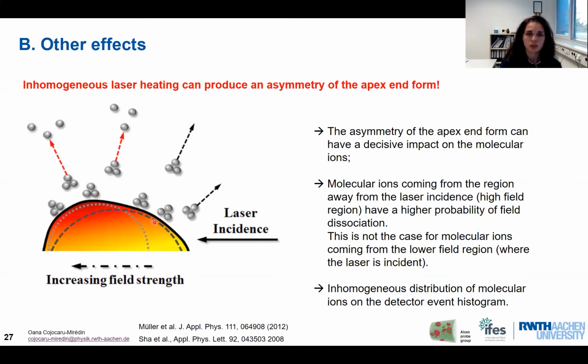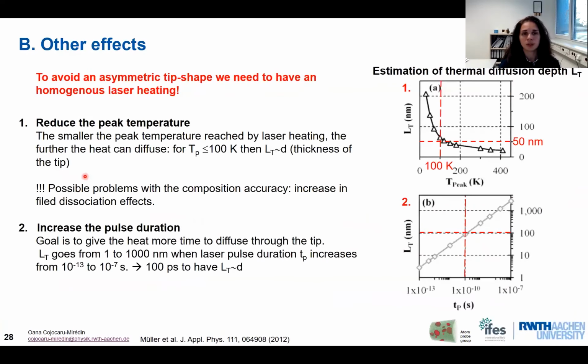And because of this inhomogeneous field distribution, if we have molecular ions which are going to be evaporated, here on this side we are going to see on the detector event histogram a decent proportion of molecular ions. And on the other side, because the field is much higher, these molecules are going to dissociate, and we are going to see a much lesser proportion of these molecular ions on the detector event histogram. So how do we avoid asymmetric tip shapes, inhomogeneous laser heating, and an inhomogeneous field distribution on the apex of the tip?